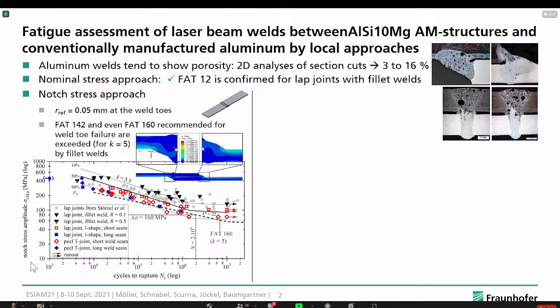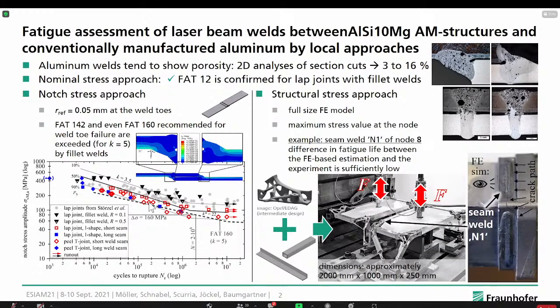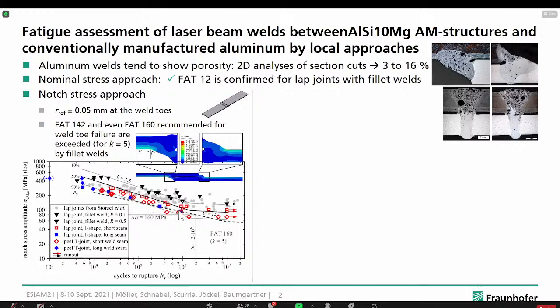What we see here in the notch stress diagram versus cycles to rupture is the outcome of the numerical simulation of these welds, and especially we see that these fillet welds, which we see here in the numerical model, which have the fatigue failure starting from the weld toe, the black symbols, are in good agreement with the gray circles from previous investigations on conventionally manufactured aluminum welds, while these run-through I-shape laser beam welds are in the lower part of the SN curve and do not really fulfill these recommendations.